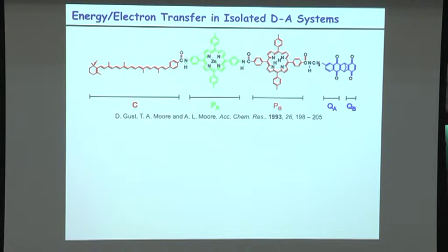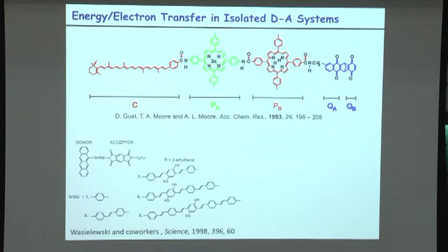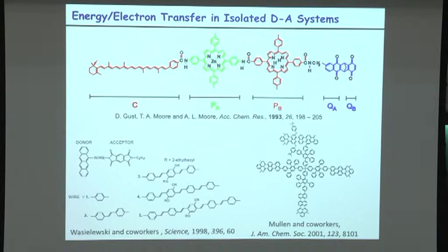But although it is very difficult to synthesize these molecules, the final goal they wanted to achieve, a long-lived charge-separated state, was not achieved because they are all connected and you do not have these systems propagating the charge to any other dimensions. Since then, many groups started working in this direction wherein they put some bridge of different lengths to figure out whether that will matter for the charge recombination rates. This is again work published from Northwestern University by Wasielewski and co-workers, somewhat similar to the DNA work that I have shown. Here the wire is oligophenylene.